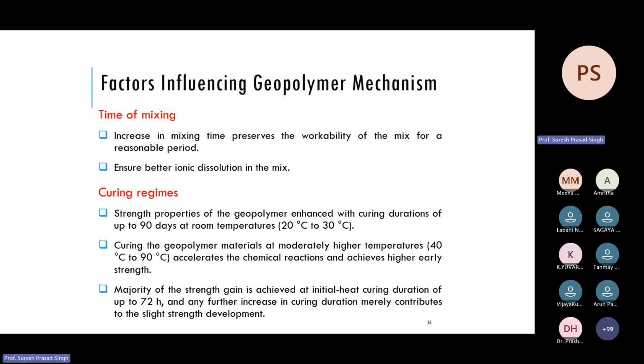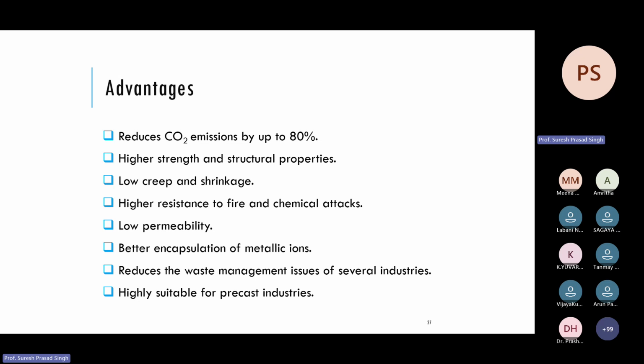Initially, as I told, at any temperature above the freezing point of water, it can develop the strength, but it is found that initial heat curing is very much beneficial. Then the advantages of this geopolymer: it gives an 80% reduction in carbon emission, higher strength and structural properties, low creep and shrinkage, higher resistance to fire and chemical attacks, low permeability, better encapsulation of metallic ions.